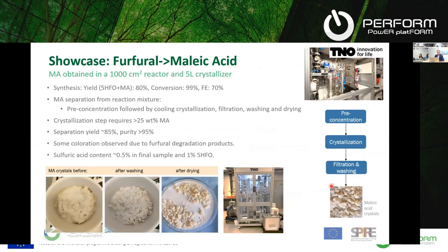So, for example, one slide is a showcase where we go from furfural to maleic acid. This was done on the 1,000 square centimeter reactor, just to prove that this can be done. We had a yield of the intermediate plus the maleic acid of 80% with a 99% conversion and a 70% faradaic efficiency. So that's the measure of how many electrons and how much energy goes into the product.